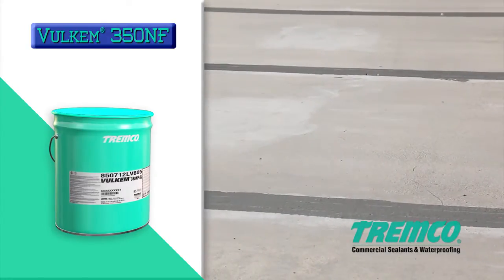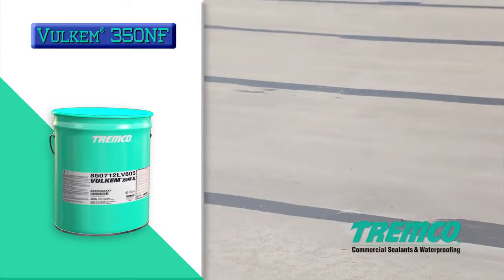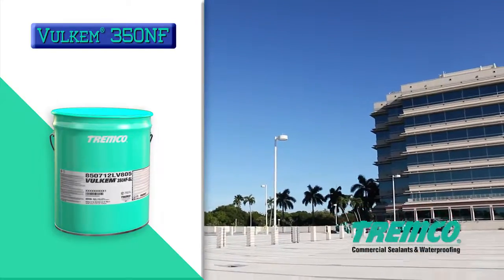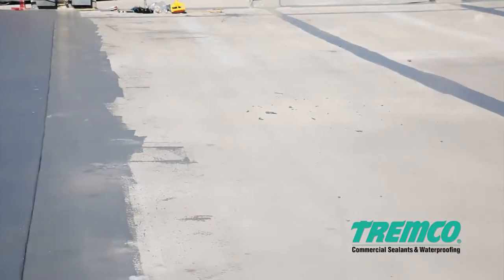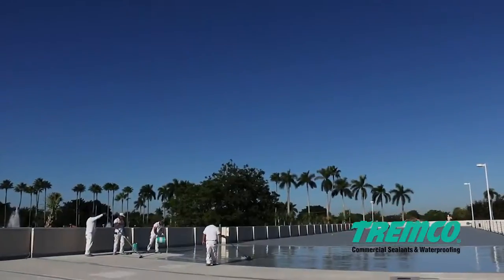Apply a 25 mil thick detail coat of Vulkem 350 NF roller grade, 6 inches or 15.24 centimeters wide, centered over all untreated cracks, all routed and sealed cracks, and over all cold joints. Feather edge the terminating edge of the detail coat to prevent these edges from showing through the finished coating.